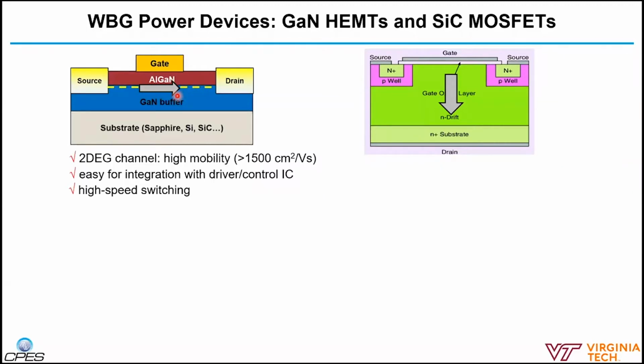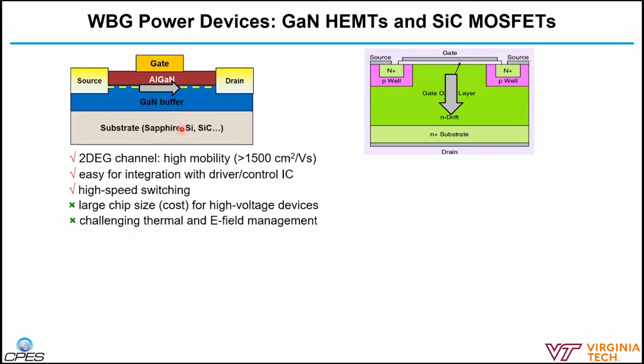A key feature of this HEMT is that it has a two-dimensional electron gas channel, which is a quantum well channel that allows very high electron mobility. Electrons are confined in this two-dimensional conduction and have very high mobility, and because this is a lateral device, it's easy to integrate with ICs and also allows high-speed switching. But the drawback is that if we want to make very high voltage devices, we need to increase the gate to drain distance to support a high voltage, and that makes the chip size very large. The other thing is the current is conducting in a very narrow channel just several nanometers wide, so thermal and electric field management is relatively challenging.